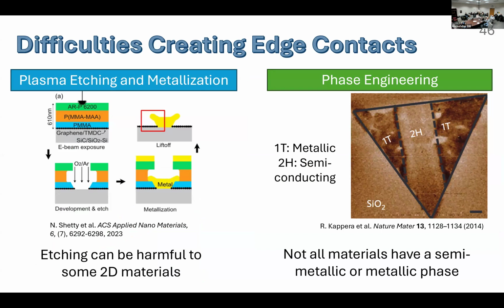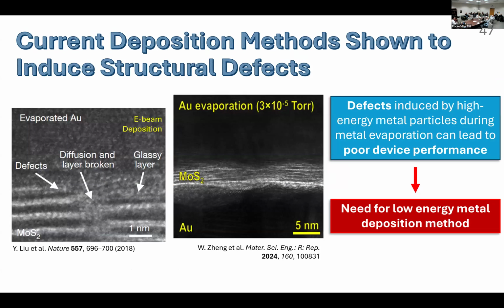The issue with this is that etching is not suitable for all 2D materials. Some 2D materials are more sensitive to it than others, so it's not a method that can be used for all materials. The other method, phase engineering, is also not applicable to all materials, as not all materials have a semi-metallic or metallic phase that they can be converted into. And as I mentioned, our current deposition methods are shown to induce structural defects that can negatively affect the device performance of our transistors. So this has caused the need for a low energy metal deposition method.